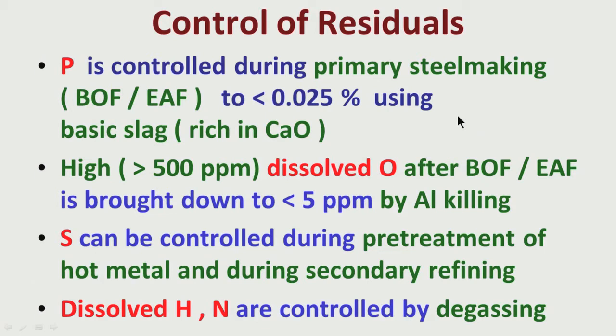We can take care of phosphorus by using a basic slag rich in calcium oxide (CaO). The basicity — the ratio of CaO to SiO₂ — has to be at least 2 or 2.5. Phosphorus in the presence of oxygen forms P₂O₅, which is acidic, and CaO being basic will take care of it. So with sufficient CaO in BOF or EAF slag, the phosphorus level can be brought down in steel to less than 0.025%.